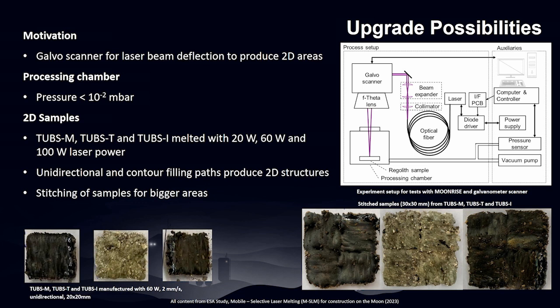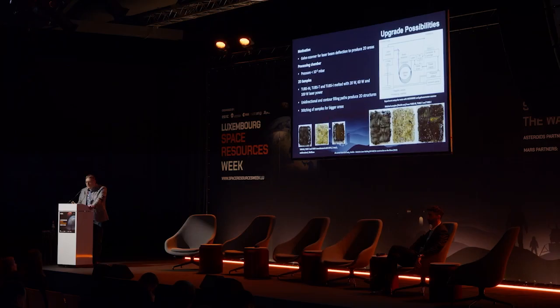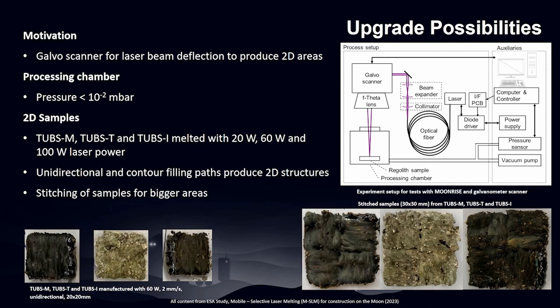We tested different processes with unidirectional laser beam or contour filling paths, and produced two-dimensional structures the size of 20 by 20 millimeters. Also, we tested the stitching of these samples to bigger areas to make sure that we are able to produce stable and crack-free materials from different types of regolith, which we expect to find on the landing sites of the future missions. We use for that the original laser system, which we also plan to fly to the lunar surface. You see some samples on the right side. These are the stitched samples of 30 by 30 millimeters.